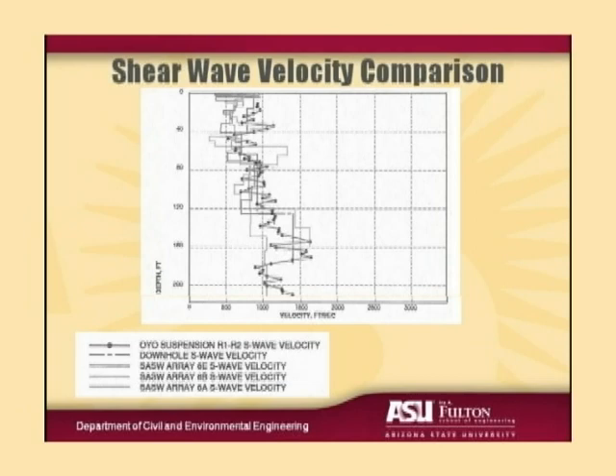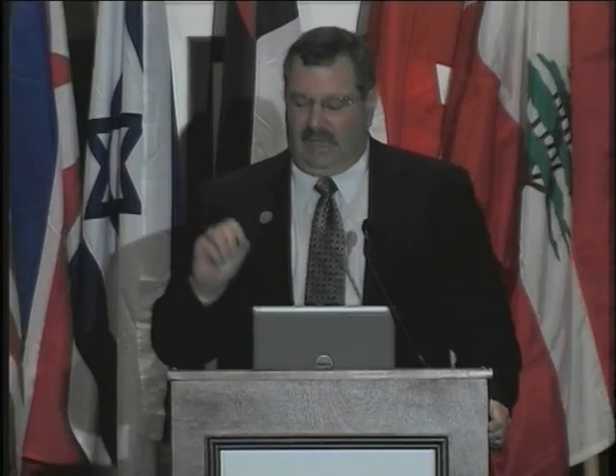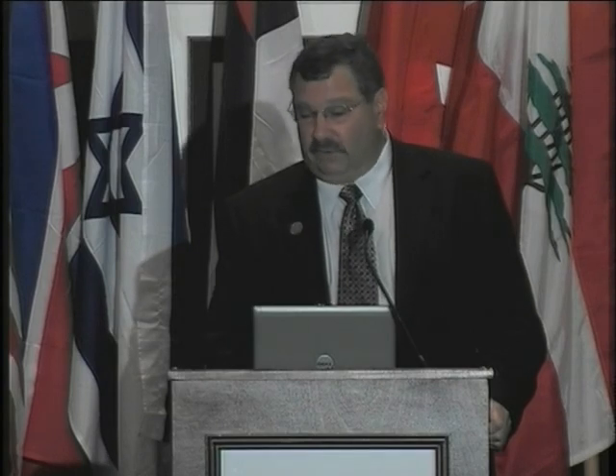Well, fortunately, SASW, I think people have generally accepted now. In 1996, I think it was still considered a relatively new technique. But where the seismic station was on top of the landfill, a previous consultant had put in a deep boring and had made downhole shear wave velocity measurements and measurements using the OYO suspension logger, which again was a relatively new technique at the time. So we were able to compare the shear wave velocity profiles from SASW to these other 2 techniques, and as this figure demonstrates, we got very good agreement, and so we were able to move ahead using the SASW data with good confidence that it gave us results that were comparable to other geophysical techniques.